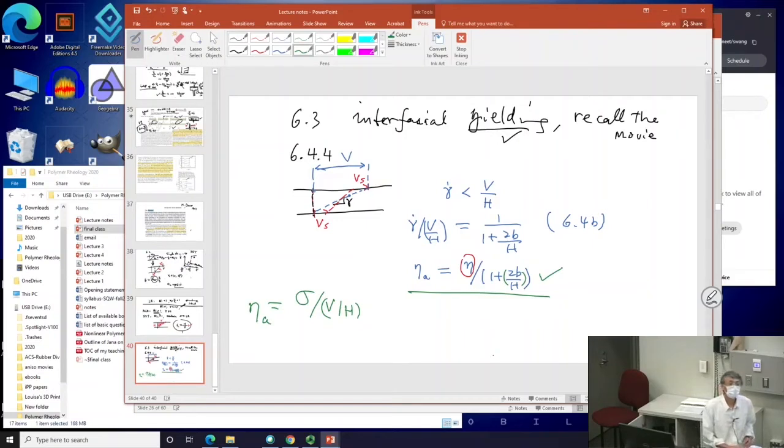So there was a rule of thumb, a convention: instead of peeking into it, which is so hard to do typically, 1 millimeter, you have to have a setup, I will describe that later. It's difficult to do, so let me be cheap. I will just vary my gap and see if my result depends on the gap. The notion there, incorrectly, and it really amused me, was to assume that this B, as I vary the gap, will not change. Then there will be a gap H dependence, by definition.